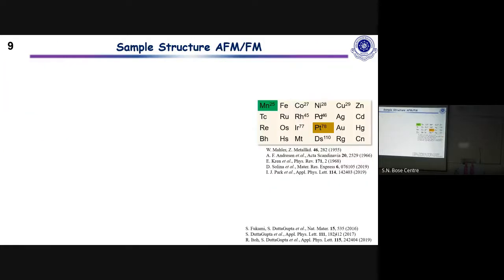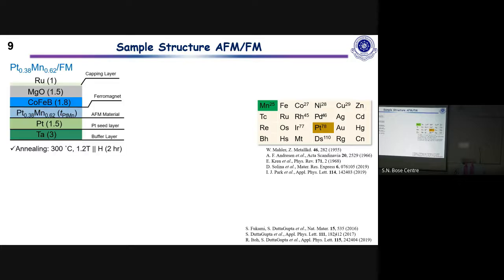So what we did was we looked into the literature for what material we can use, and we found that there is a very well-known material, which is an alloy of platinum and manganese, which has been used by the industry for a very long period of time for a different purpose, of course. But it can be very easily grown. It has a Néel temperature above room temperature, and it has a very simple face-centered tetragonal structure, and can be very easily grown with sputtering. So we took this material and we grew this bilayer by sputtering. And in this case, the thickness of the cobalt iron boron was such that the magnetization is lying in the plane. It has an in-plane easy axis.